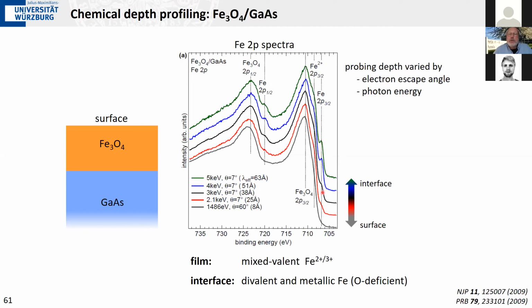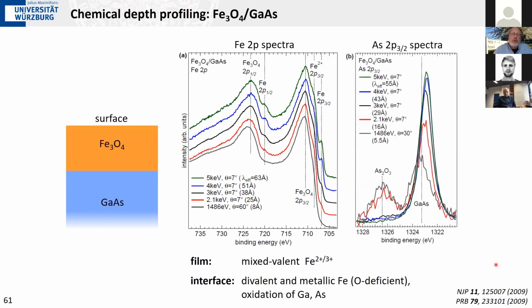But as you go towards the surface, everything looks a little bit more like magnetite. And you can also look on the other side. You can then probe the core levels from the gallium arsenide. And again, you can now change the surface and interface, in this case, the bulk and the interface sensitivity. And you find as you probe more and more the interface, you get this satellite here in the arsenic 2p spectrum, and that's a fingerprint of oxidized arsenic.